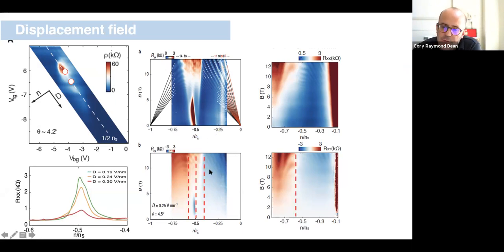And if we focus on the Hall resistance, what we see in the middle column is that when we have a well-defined insulating state at half filling, we identify that actually the Hall resistance inflects 3 times at that point as we dope around that half filling point. And in the case where we have no insulating feature at half filling, the Hall resistance doesn't really show any feature at that point. We do see an inflection in the Hall resistance at some value, but that occurs at a different value that does not coincide with half filling per se.